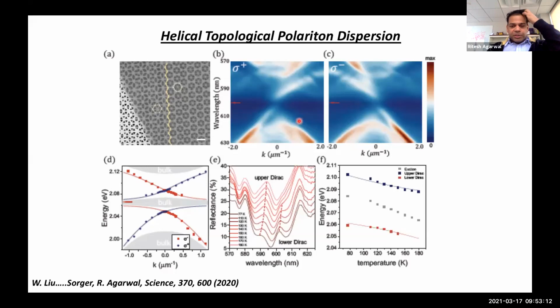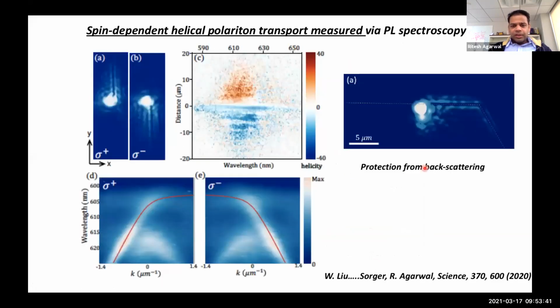Polarized reflectance spectroscopy shows what was expected, thankfully. These are the bulk bands, and the interface modes in the reflectance spectroscopy also show these circular polarization dependent modes. Left circularly polarized light lights up one particular interface mode. These are topological polaritonic modes. And then the other circular polarization lights up the other interface mode. And these can be tuned with temperature.